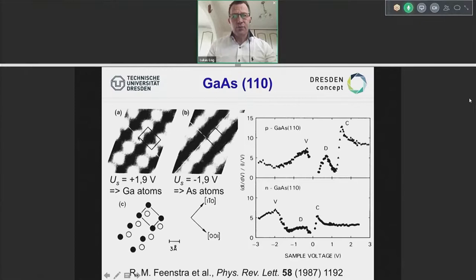Making the following experiment, tunneling either with a sample bias of plus 1.9 or with a sample bias of minus 1.9. If you digest what's happening when you bias your sample positively, you're going to have electrons tunneling into the gallium plus atoms. That's exactly what happens. You're probing the gallium atoms, which are here, while for negative bias, it's the arsenic atoms. Or in other words, if you superpose these two lattices, like done here in this cartoon C, you see nicely that the central points don't overlap. The arsenic atoms are the bright ones here, in between these two. And exactly like if you do X-rays, you are able to reproduce where the positions of these atoms are.